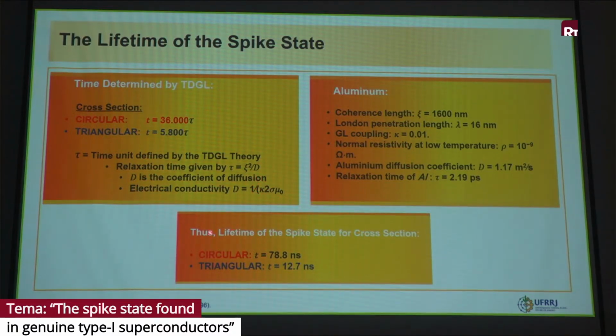So with this, we can calculate the time, because the relaxation time is tau xi square over D. D is the diffusion coefficient. Okay, so the lifetime for the circular cross section is 78 nanoseconds, a very short effect, and for triangular 12 nanoseconds. So we can see that there is a formation of a giant vortex and the annihilation of this giant vortex in a very short time. For circular 78 nanoseconds and triangular 12 nanoseconds.